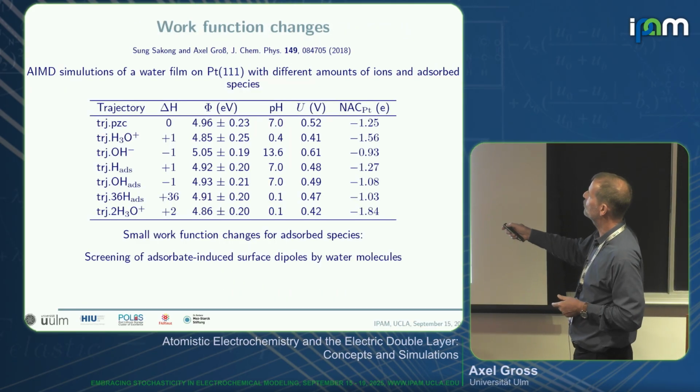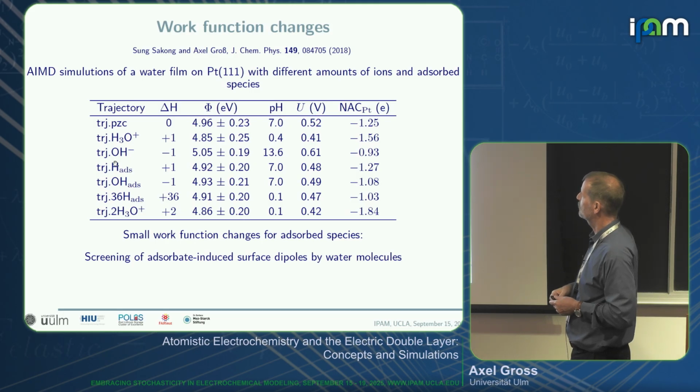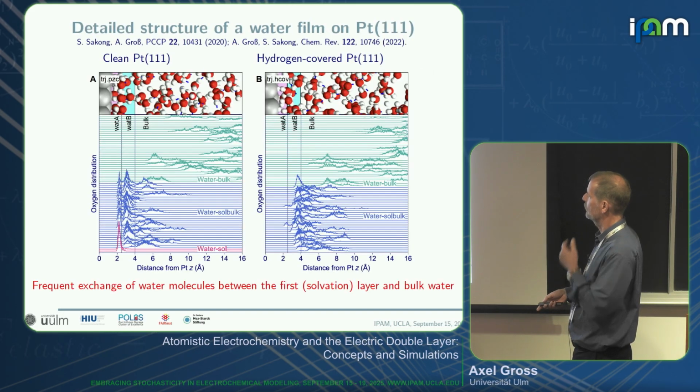And now here you see what we do, and the problem of course is we change the pH strongly, but if we add 1 hydrogen atom in our cell, we change the electrode potential by 0.1 volts and then have different conditions there. So, okay.